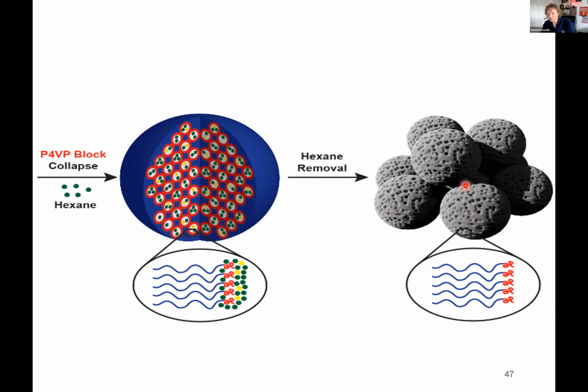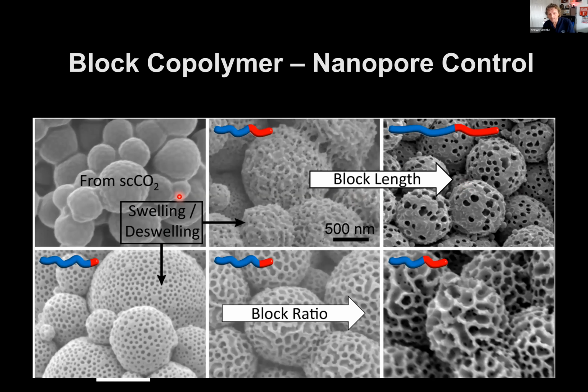We did a whole series of work that showed we could control the porosity of just the polymer materials. Here you can see we've used different block lengths and different block ratios to control the pore sizes. We're just beginning to build up our understanding of how we can control these pore sizes to create some very finely controlled porosity inside these microparticulate materials.